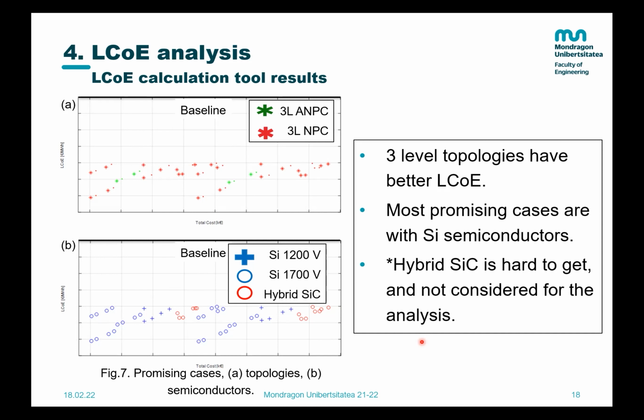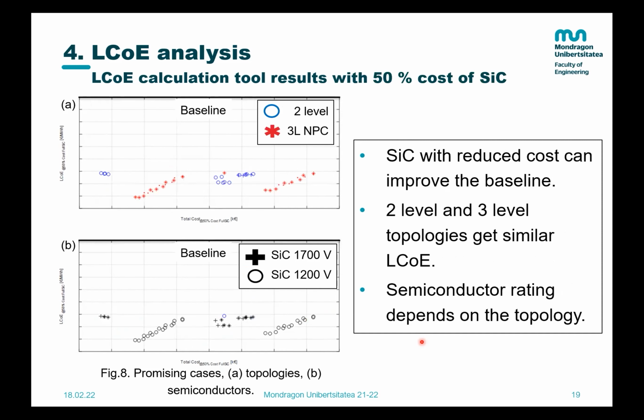Of course, the project is all about analyzing the impact of silicon carbide. So we decided to specifically analyze the configurations with silicon carbide. And we saw that the cost of the silicon carbide was holding back those configurations. So we decided to reduce the cost 50%, 1/2, and analyze the configurations with silicon carbide now.